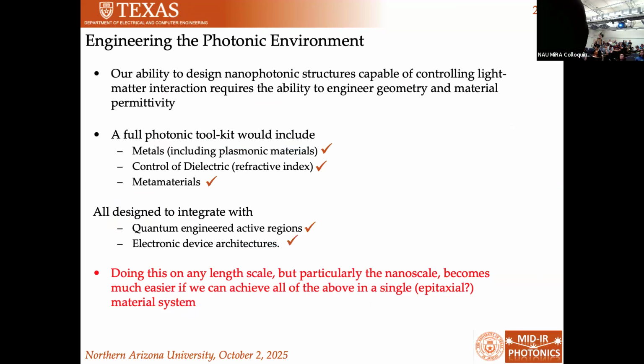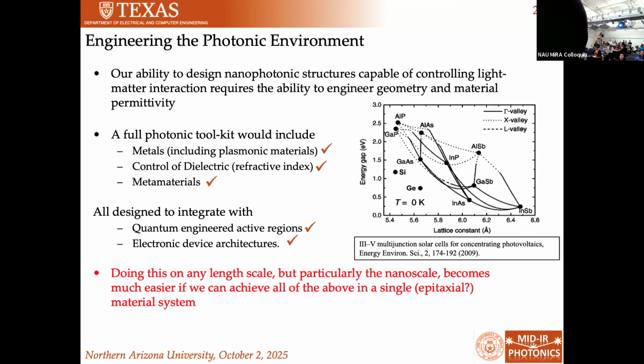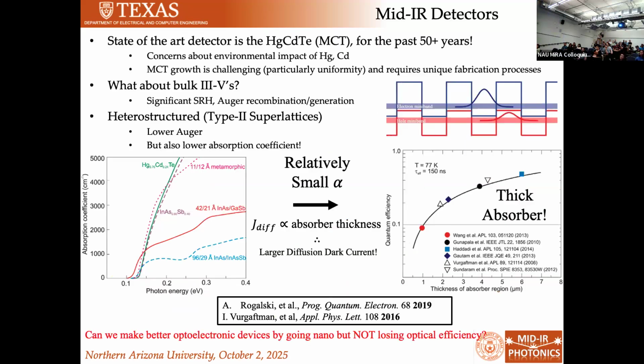And we really need to be able to do this in the same material system. I didn't mention it, but it is in fact the case that everything I showed you here is using the so-called 6.1 family of semiconductors. So we can make emitters and absorbers and plasmonic material and low-index material. We can do this all in the same material system, and we can do this epitaxially, so we can do this with the highest quality semiconductor crystals that you can get. So we have all these capabilities now, right? So how do we employ them?